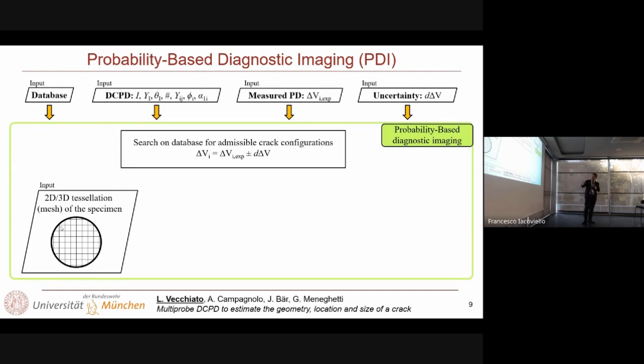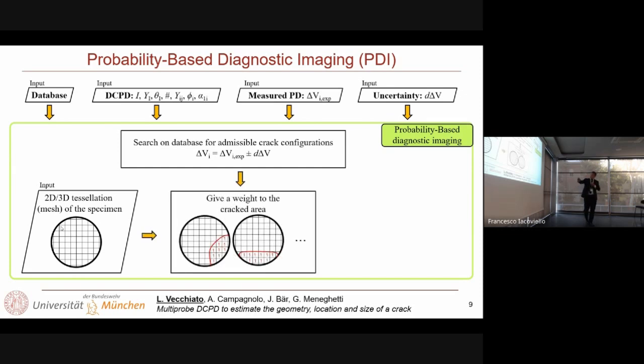Let me explain another way. We enter our database with the measured potential drop plus or minus the uncertainty, and we search for all crack configurations in the database that fit the values of the potential drop measurements. At the same time, we create a picture of the fracture surface. In this case, we have a planar crack, so it's just a 2D picture. Otherwise, for 3D crack propagation, we can use voxels, so a 3D model. Thereafter, for each configuration we have found, we create a new picture where we highlight the pixels having the cracked area. So we will have many pictures highlighting the cracked area with a 1 value for the cracked area and a 0 value for the ligament sections.